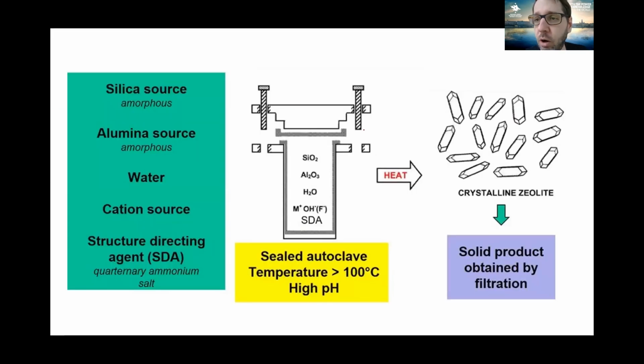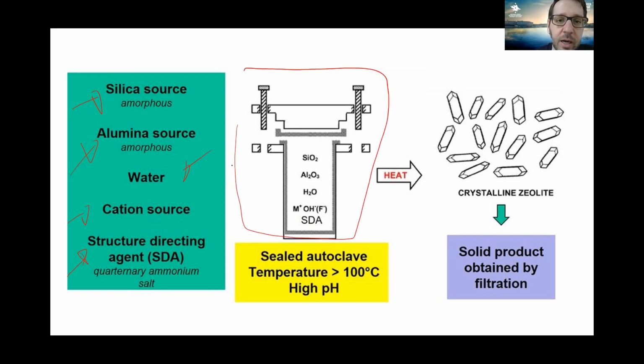So here is an example of a synthetic strategy for the synthesis of the zeolite. It's an aluminosilicate, so it has a precursor that contains silica, a precursor that contains alumina, and water. It has some cation source, which we will see is important as well. And then also a structure directing agent, which also acts as a template to dictate the porous structure. So these precursors are added into a reactor system in which the hydrothermal conditions will take place. In this case, it's a sealed autoclave over 100 degrees Celsius in temperature at high pH.